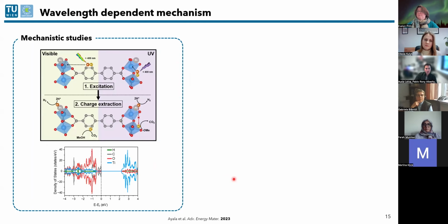So great results. And we also wanted to find out a little bit more about the mechanism and why this is so active. We did some PL studies and radical trapping studies. And there's a lot that was done, but just summarizing, we found out that we had a dual excitation mechanism. So depending on the wavelength that we were using, when we excited with visible light, we had just enough energy to excite electrons from the valence band that was at the linker to the titanium conduction band. So we had a ligand to metal charge transfer, and then for the charge extraction, these two SBUs were helping to get the electrons to the photodeposited platinum nanoparticles to catalyze the reaction. So we had this charge separation, which is what we wanted.